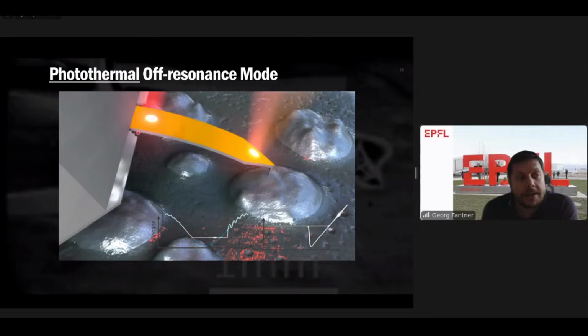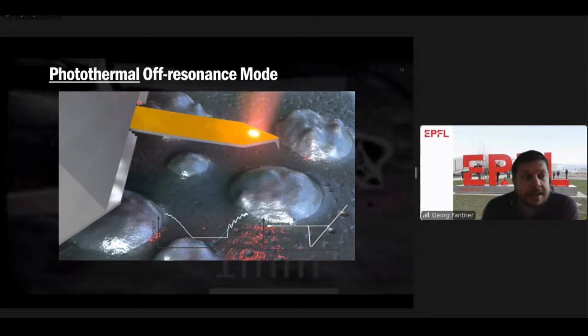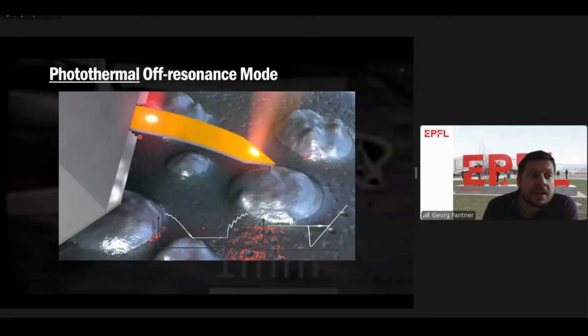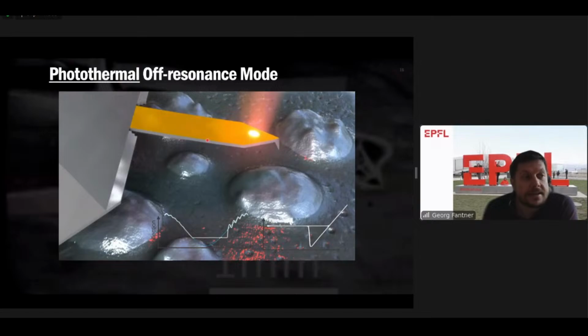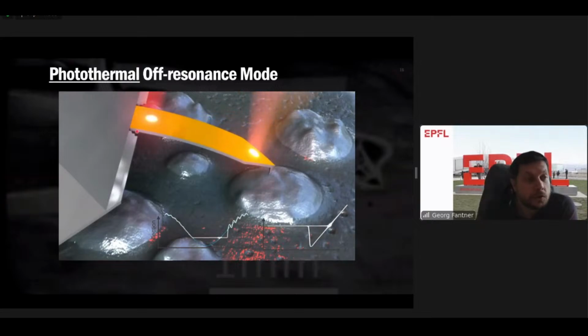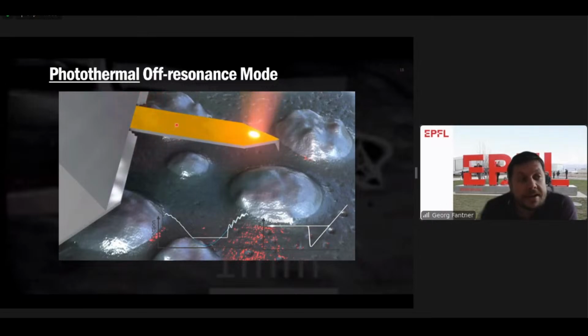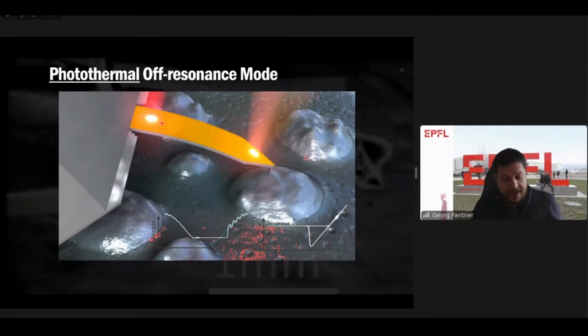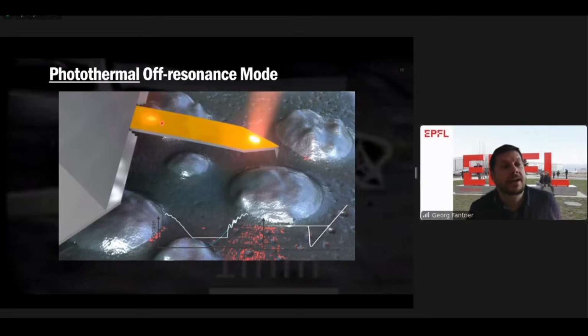And so we are locally heating the cantilever with the laser. Because the cantilever consists of different materials, the base material, in this case silicon nitride, and on top a metal layer, in this case chrome and gold, when there's a local increase in temperature, these materials expand differently, and we get this bimorph effect, which will actually bend the cantilever down.